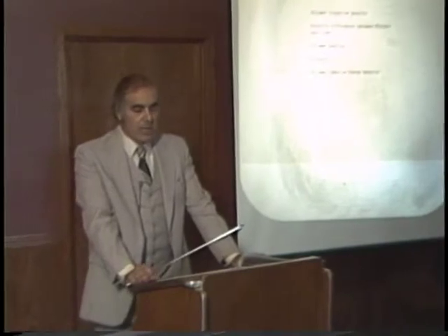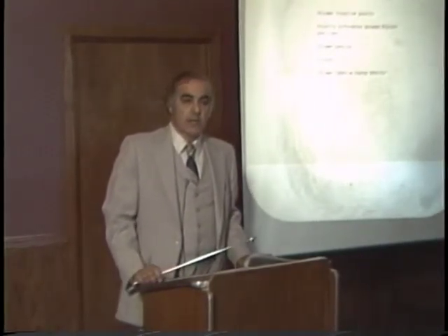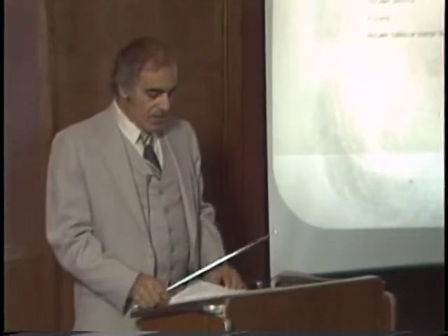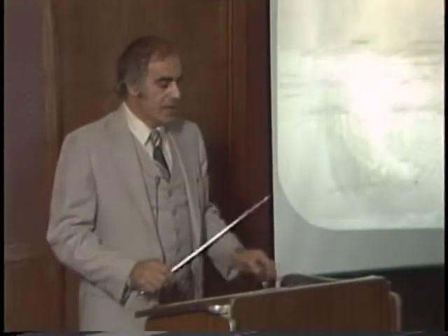In the course of our work, we've uncovered a number of factors that affect the barrier properties of the liners that we were dealing with. First of these is polymer crosslink density. This is how tightly the polymer system in a liner is chemically cross-linked. The second deals with polarity differences between the migrant and the liner that we're using. Polymer density, this is the actual weight per unit volume of the polymer system that we're dealing with. Filler effects, and finally, polymer cohesive energy density. Have the next slide, please.